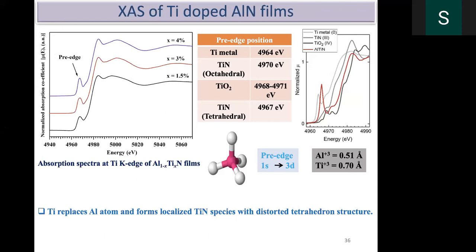Particularly, what we have understood from the pre-edge peaks is that the titanium sits in the place of aluminum. We did not get pure titanium or titanium clusters, and TiO2 also did not form. Either TiN or these two are very close by. So this titanium atom replaces the aluminum, and a slightly distorted tetrahedron structure forms in the system. From this, the bond length and the number of atoms close by can be found out from X-ray absorption spectroscopy. That's what I wanted to show here.